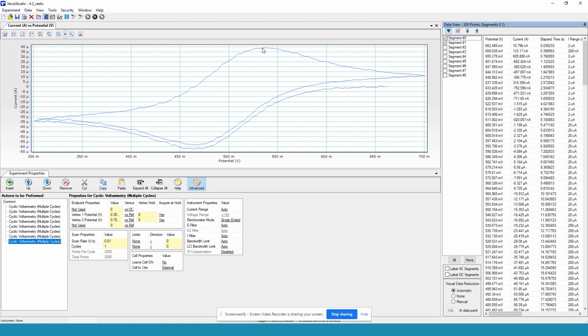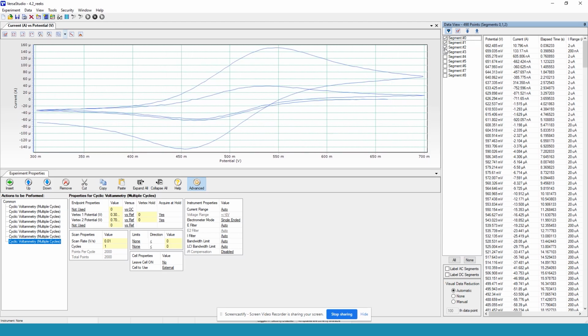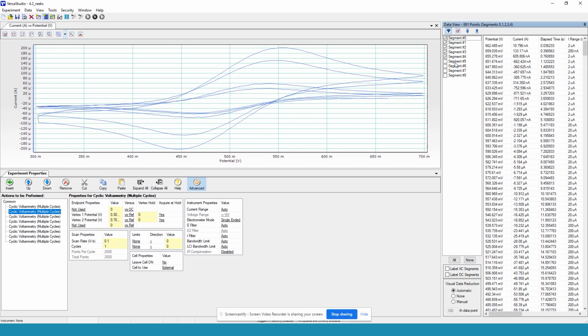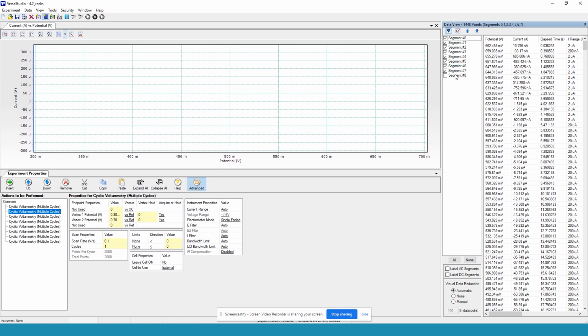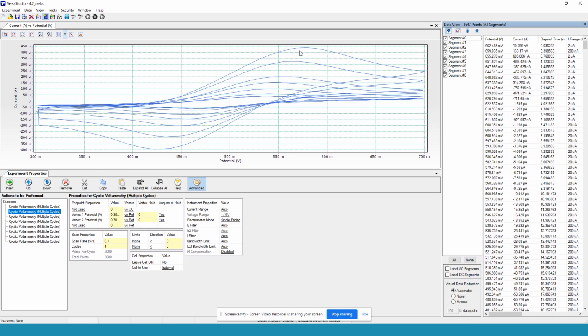We can look at the peak current of this experiment and see that we had a peak current of about 40 microamps. And if we compare this to the second experiment, which was done at 100 millivolts per second, we can see that in the second experiment with the higher scan rate, we have a much higher peak current that's close to 160. So we can see that indeed the scan rate has a quite significant effect on the position of the peak in terms of its voltage and its current.